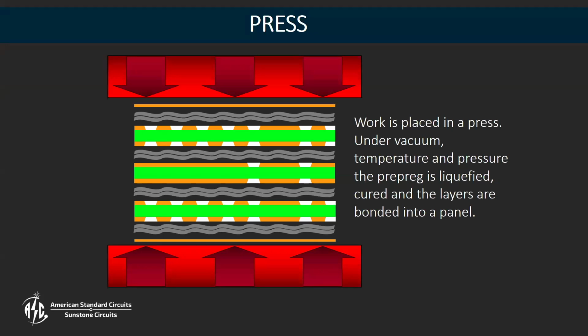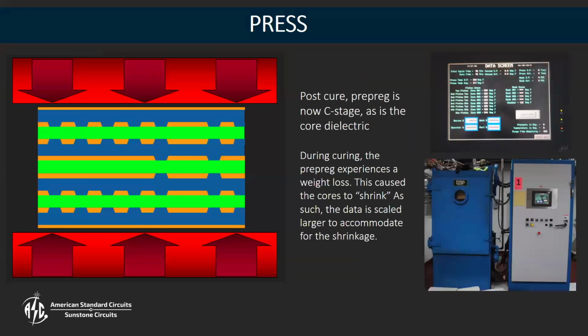So we're applying that heat and pressure, and it dwells in there for a period of time. And then after that, that heat excursion happens, and the panels start to cool down at a controlled rate. Those pre-preg layers that we put in there are now basically the same epoxy makeup as the cores were. So it's what we call C stage of that cycle. It's all cured and hardened and adhered to the copper via the oxide layer, and everything at this point is really solid and well done.